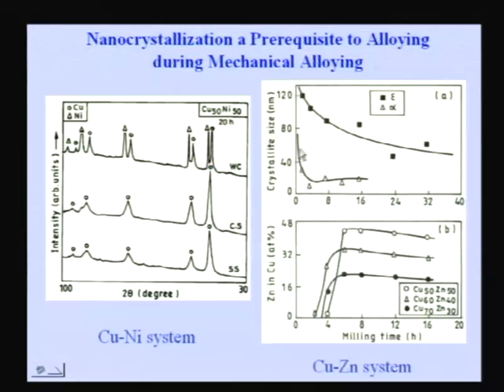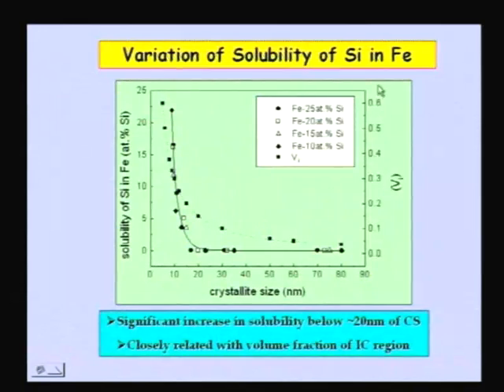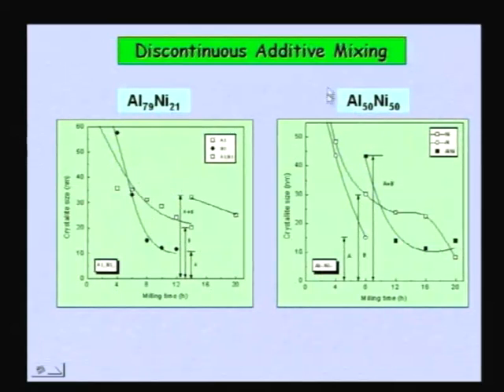So when the crystal size decreases to a critical value, suddenly the solubility occurs. This is true whether it is a copper zinc system or copper nickel system, or this is iron silicon system. So, the solubility of silicon in iron suddenly increases when the crystal size comes below 20 nanometers. Up to 20 nanometers there is no solubility, below that suddenly there is a solubility. So, this we have already talked sometime, and then discontinuous additive mixing is another which we talked.